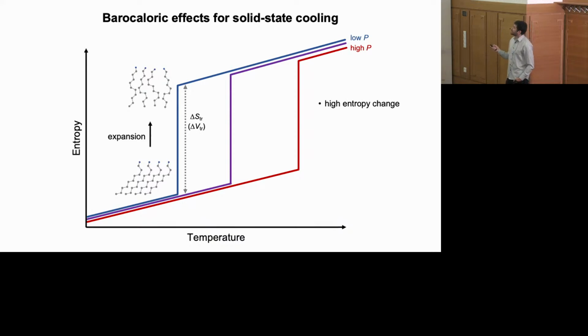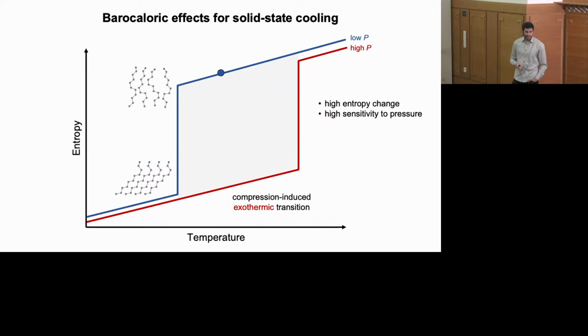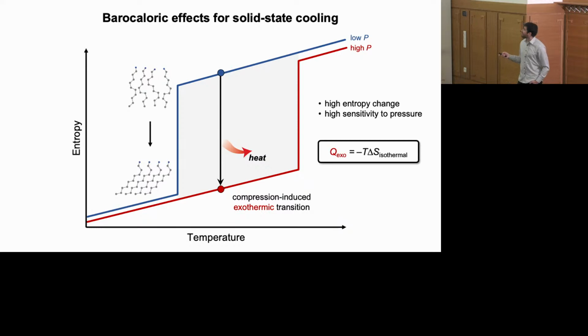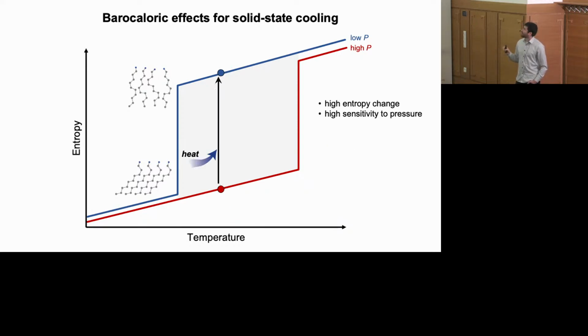And so if you have a material that undergoes a large entropy change, meaning you can withdraw a large amount of heat in a given cooling cycle, and high sensitivity to pressure, then you can imagine employing the type of cooling cycle I showed on the last slide, where you have an increase in pressure that drives an exothermic phase transition that allows you to dissipate, that can then be dissipated, that excess heat to the environment. That transition can be reversed to induce cooling, and then you can drive this cyclically between these two different states to drive a cooling cycle.